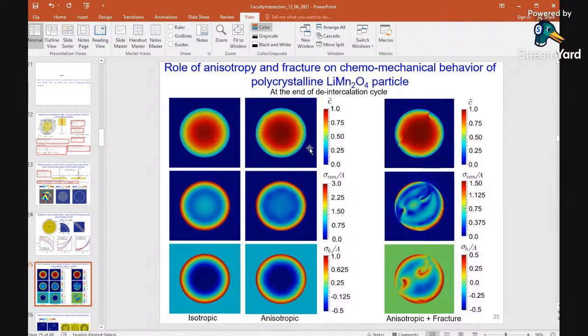Now for the next part, we put the crystal as anisotropic. You see that there is a little disturbance within the concentration field as well as the stress field, and the anisotropic hydrostatic stress is generated. We must remember that the gradient of the hydrostatic stress field is very important for the stress assisted diffusion, not the stress itself.